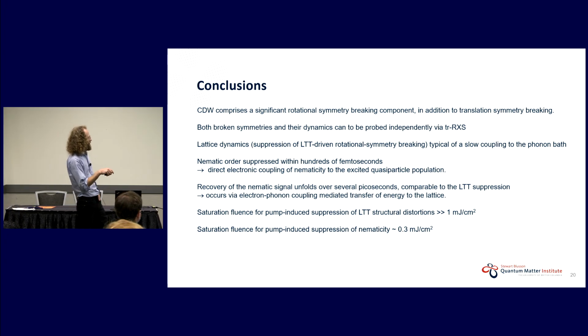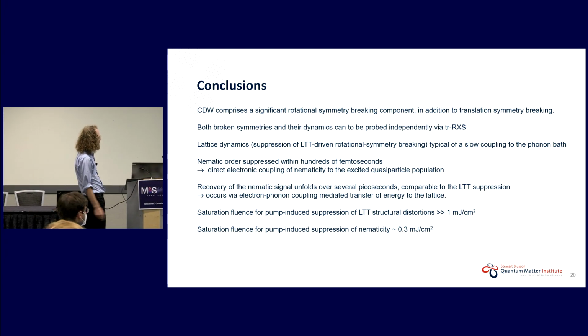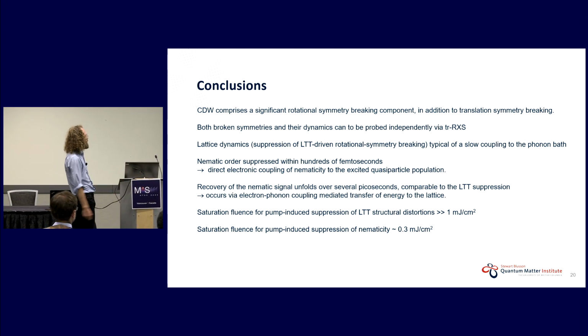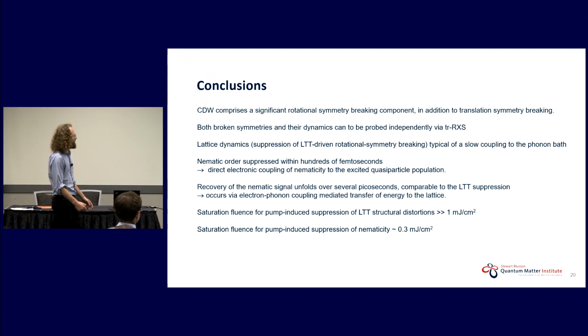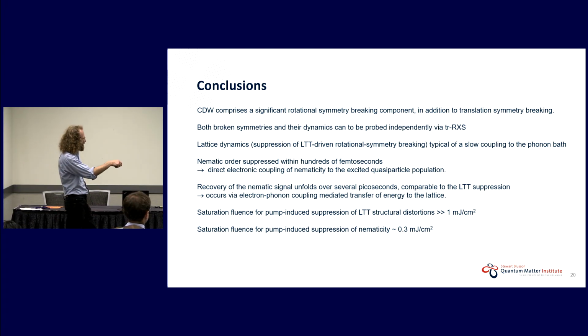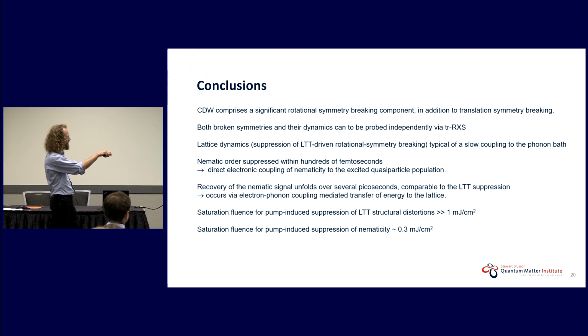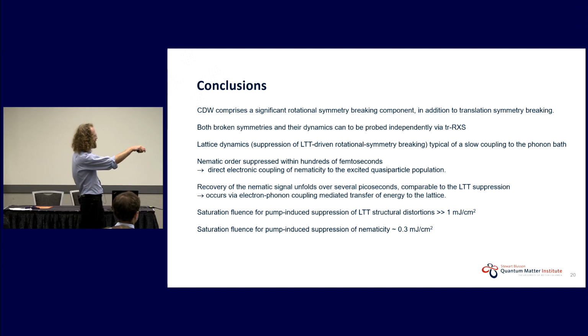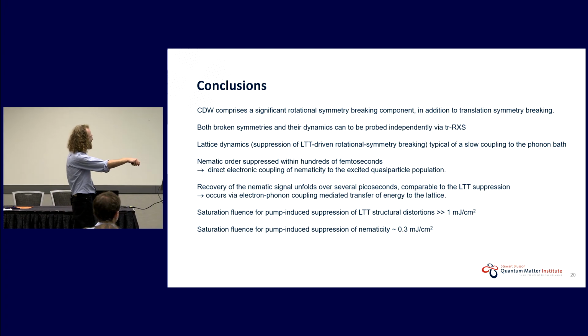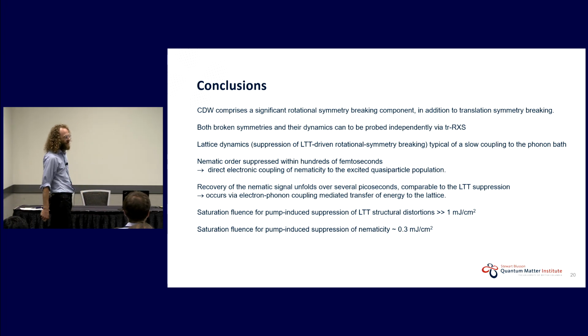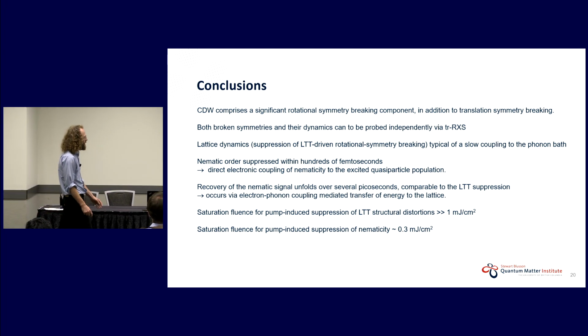The nematic order is suppressed much more quickly, showing a direct coupling between the excited quasiparticle population and that nematic state. And then the recovery of that electronic nematicity goes over a time scale similar to the suppression of the LTT. And we have these two different fluence dependencies, which can also be used to separate the two.